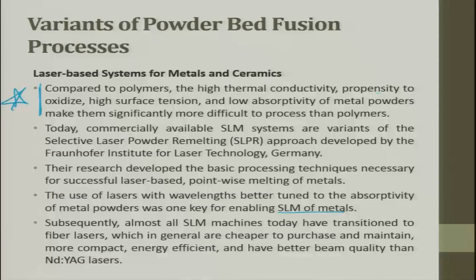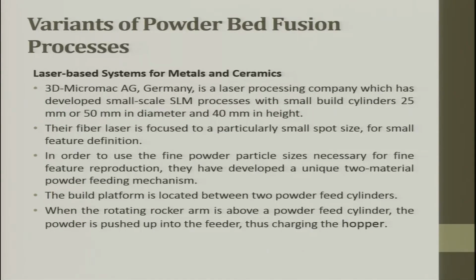Okay. And when you talk about laser material interaction, it is the absorptivity property which plays an important role. Subsequently, almost all SLM machines today have transitioned to fiber laser, which in general are cheaper to purchase and maintain, more compact, energy efficient and have better beam quality than Nd:YAG laser. 3D Micromac AG Germany is a laser processing company which has developed small scale SLM processors with small build cylinders of 25 millimeter and 50 millimeter in diameter and a height of 40 millimeter.